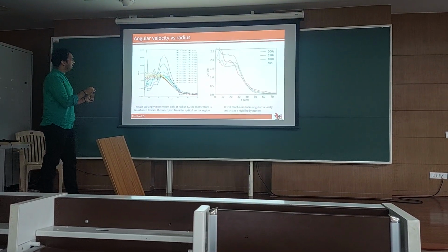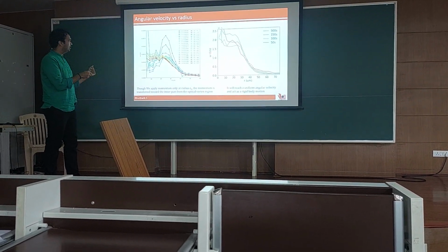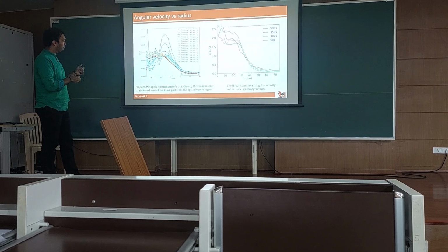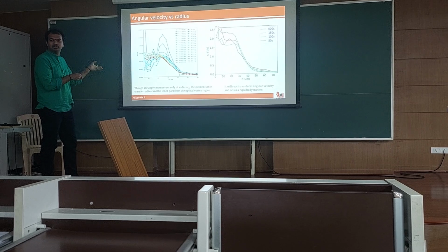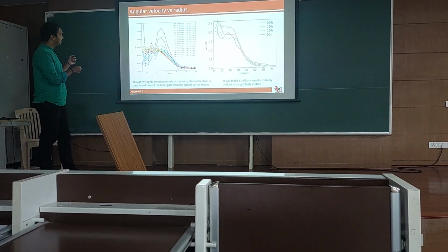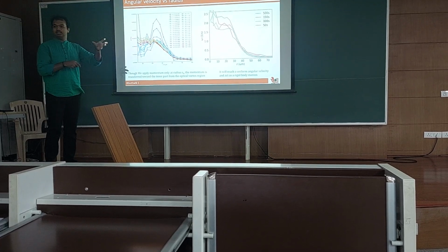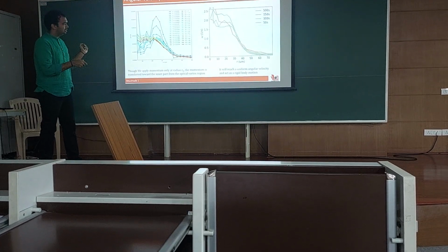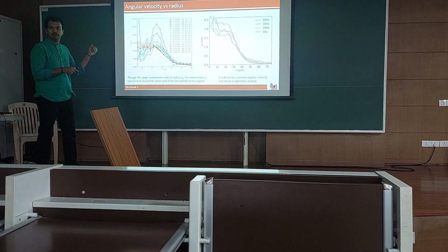In the beginning, only the particles in the trap got the angular momentum, but after some time, due to particle interaction, even the inner particles start to rotate. The peak increases and then it saturates. After some time it will saturate and the whole body acts as a rigid body. And in this region, shear banding is happening. We have different omega for different R.